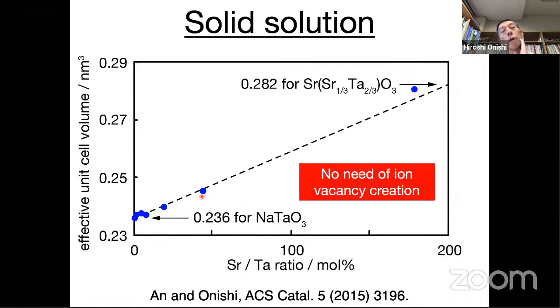So these blue spots present experimental results. And as you see, these results are well fit by a straight line from here to there. That is, the unit cell volume is linearly dependent on the concentration. This means there should be a solid solution. So here one component of the solid solution is pure sodium tantalate, and the other component is strontium tantalum oxide. This is another perovskite structure, a well-known compound in a perovskite structure lattice.